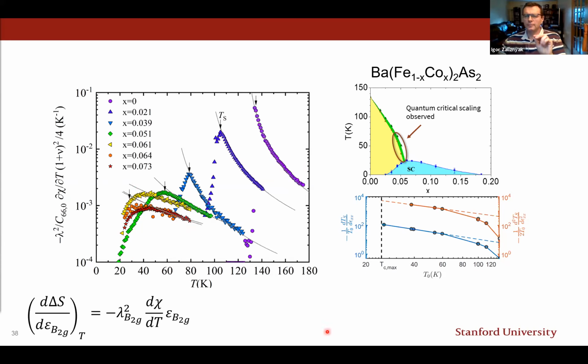So maybe just to make it clear, you are saying that this particular strain affects nematic fluctuations and does not affect the orthorhombic lattice fluctuations that would exist in an insulator in the absence of electronic nematicity. So I guess what I should say is that it is in particular also the temperature dependence of this quantity that, similarly to the elastoresistivity, basically leads us to the conclusion that it is really the nematic fluctuations that determine the response and not fluctuations from the lattice itself.